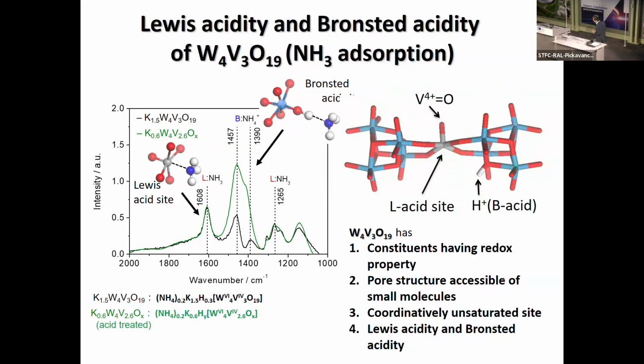For the Brønsted site, the Keggin unit has the negative charge. Normally these are neutralized by the existence of ammonium cations. But some ammonium cations can be removed under the treatment of acidic condition, leaving a proton. The proton may locate near the Keggin unit. So the material can possess the Lewis acidity, Brønsted acidity, and redox properties due to the vanadium and the coordinatively unsaturated state here. So such a structured material can already possess such catalytic functions.